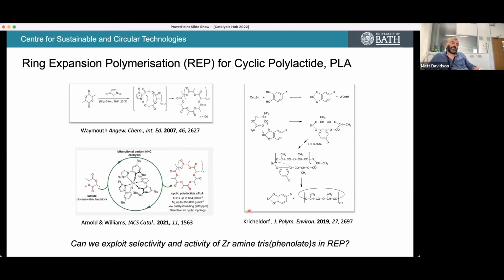But really where we got interested in these cyclic polymers, and you'll see why in a minute, is reports that Kricheldorf in Germany has been generating for, I would say, probably 5 to 10 years now, looking at tin catalysts, so tin octanoate, and these tin catecholate species in particular are really interesting ones. Where you generate this tin catecholate species in situ, up here somewhere, and you do the ring expansion polymerization, and you end up with pretty pure rings of PLA.